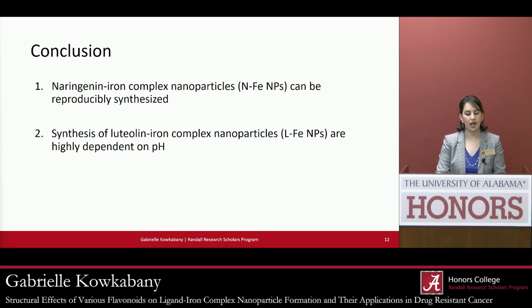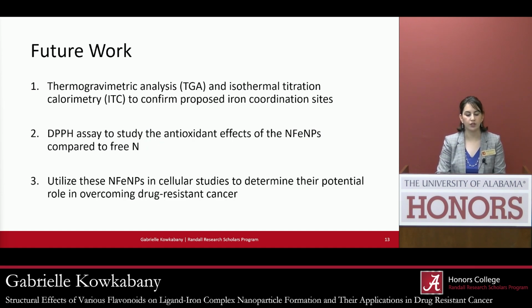So in conclusion, I was able to successfully synthesize naringenin iron complex nanoparticles with multiple ligand-to-iron ratios. And I also found that the synthesis of luteolin iron complex nanoparticles are highly dependent on pH. However, because luteolin is very stable in highly acidic conditions, it may actually have applications as an oral route because it can survive stomach acid. So we may look into further applications in that way as opposed to cellular studies.